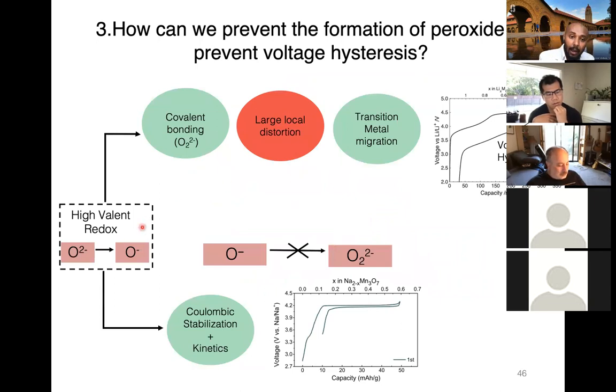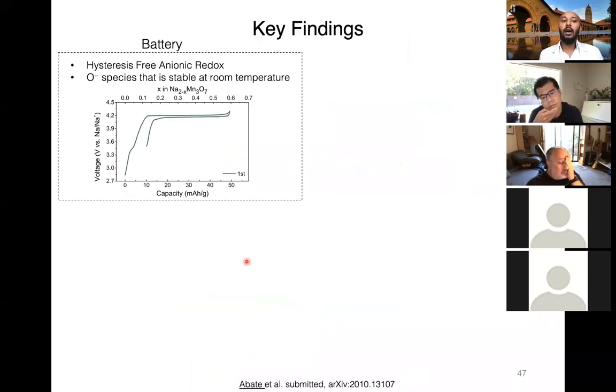So we indeed are able to circumvent this reaction pathway. We indeed are able to prevent peroxide formation and stabilize O- species. And the way we're able to do that is by improving Coulombic stabilization and the kinetic barrier through ordered defect introduction in the system. So the key findings in this work are threefold. The first one is this is the first report of a hysteresis-free anionic redox system, where we unambiguously confirmed that this O- species formation is the mechanism behind this hysteresis-free system. This is also the first report where O- species are stable at room temperature.